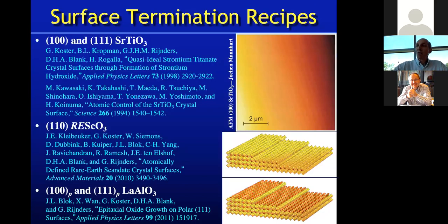Okay, now not only is it important to have a high quality substrate, but if you're trying to use these epitaxial tricks, it's important to have a surface on that crystal that is not heavily damaged. Ideally, you'd like the surface not to be mechanically damaged by the polishing process, whatever it was. And you'd like it to be atomically smooth. And you'd like to know what the very surface termination layer is so that you can then start to grow your material on top of it.